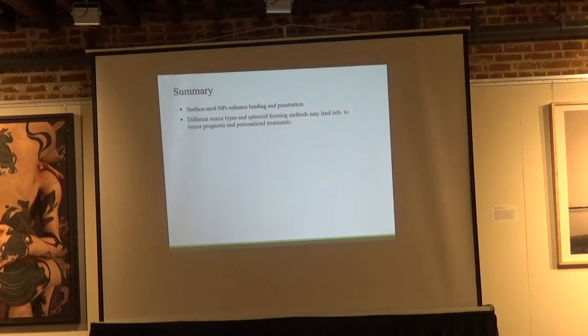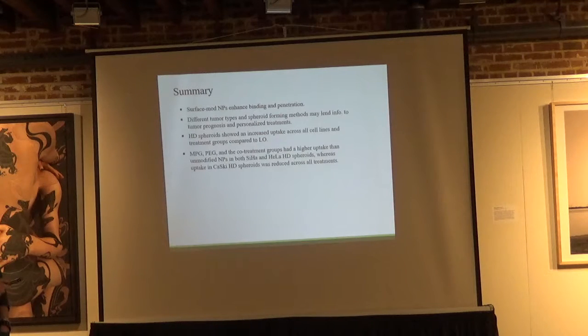So in summary for this first part, we just have the surface-modified nanoparticles, as expected, enhanced binding and penetration, and in fact, we think that the co-treatment will enable better localization depending on if you're within a close proximity to the tumor periphery or more toward the center of the tumor. And this may be used for different tumor types, and spheroid forming methods may lend info for different clinically classified tumors, is our hope. HD spheroid showed an increased uptake across all cell lines, and while I didn't show the data